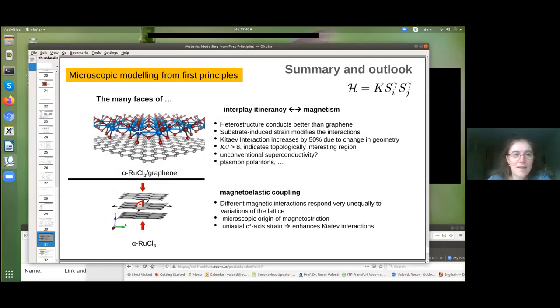My question is about the direction of the strain you use in your calculations. So here you have a heterostructure, and I expect that the strain obviously changes in plane. Is there a reason why you use the strain along the z-axis? Oh, for the second one. So, okay, in the heterostructure, indeed, because the ruthenium trichloride has to accommodate to graphene, and the bonding in ruthenium trichloride is in fact softer than the bonding in graphene. So ruthenium trichloride, in order to accommodate, you are straining along the AB direction.